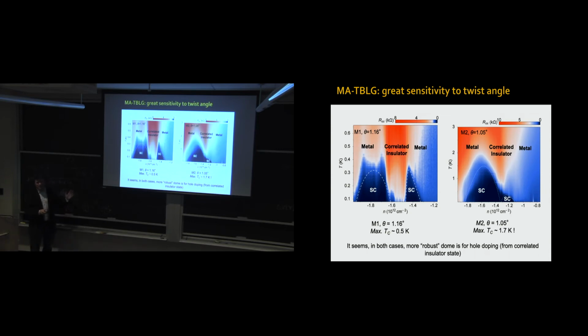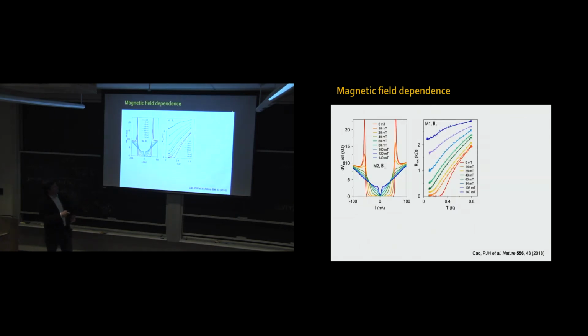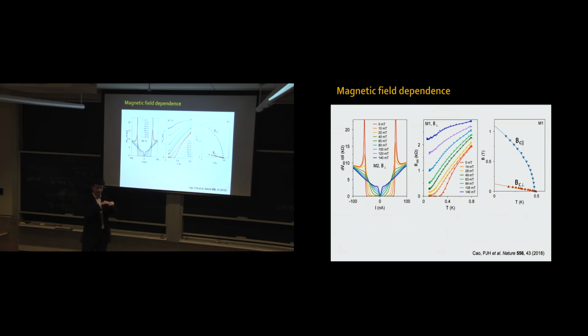This is a 2-dimensional superconductor, so you can apply a magnetic field to kill superconductivity. You can measure the resistance at different magnetic fields to extract superconducting coherence lengths. You can apply perpendicular and in-plane magnetic fields. Because it's a 2-dimensional superconductor, you can apply much larger in-plane magnetic fields, because there are no substantial orbital effects, since it's 2D.